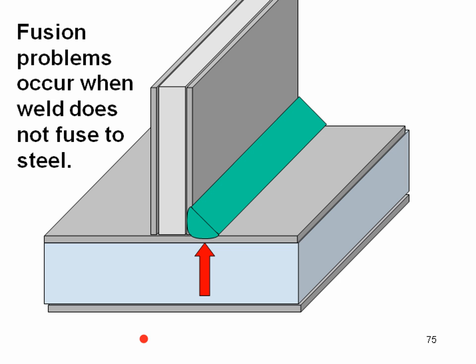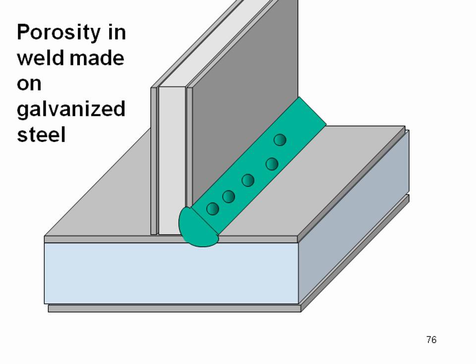Now, I'd like to suggest that's probably a less frequently encountered problem. The more likely problem is that you will have extreme porosity in the weld. Now, when you heat the galvanized coating, it actually sublimates, where we go from a solid to a gas.